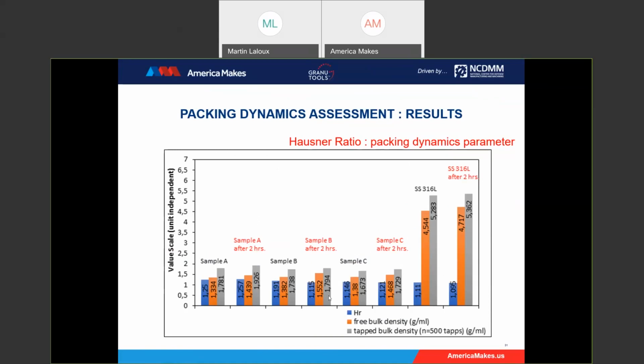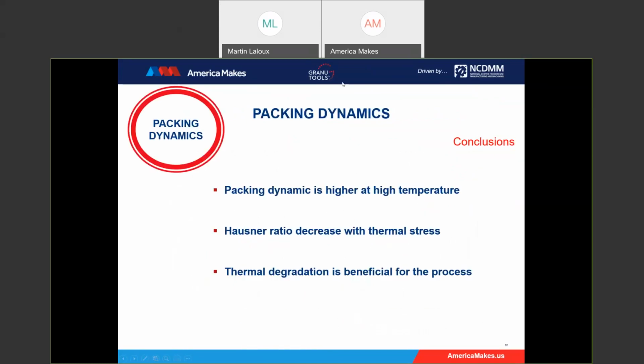So the Hausner ratio is decreasing, which is better for the AM process. The conclusion on the packing dynamic is that it is higher at high temperature. The Hausner ratio decreases with thermal stress, which is better for the additive manufacturing process, and the thermal degradation is beneficial for the process.